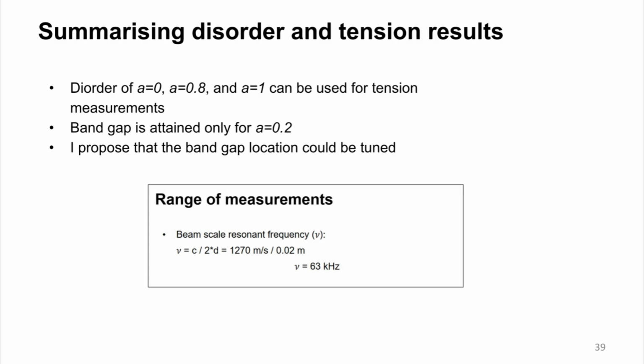I also propose that the band gap location could be tuned, and this goes back to the original calculation of range in which I should be measuring my metamaterials, and I find that band gap region appears around the 63 kilohertz, which was the original Bragg peak, and it appears after suppression of the Bragg peak in non-disordered metamaterials. And the frequency at which the Bragg peak appears depends on the interpoint spacing in the original unperturbed point cloud. So by changing the interpoint spacing in the original point cloud, we could change the location at which the band